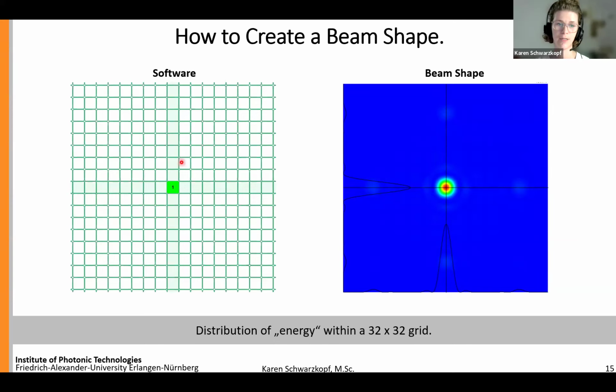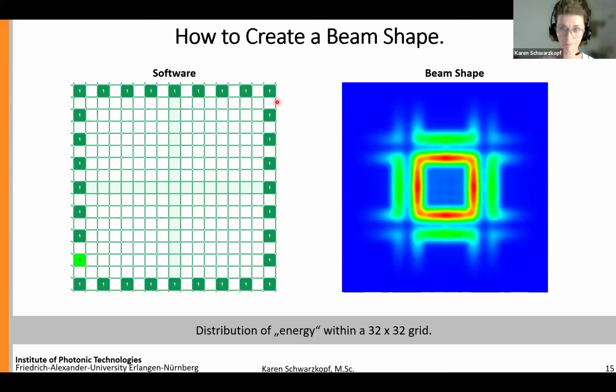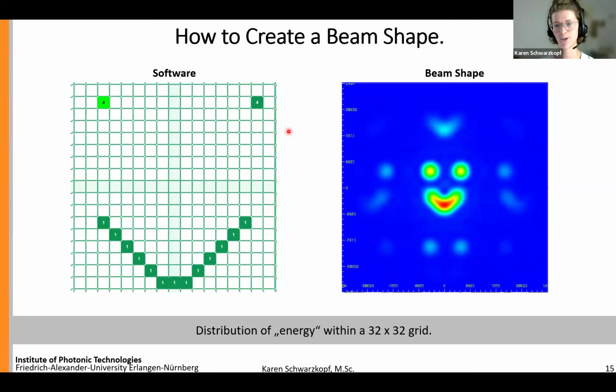What is now happening if you're starting to distribute the energy in different fields is demonstrated here. For instance, for a square-like intensity distribution, you can see by accordingly putting the energy packages in the edges, a square-like intensity distribution is created. And these two beam shapes are rather ordinary, I would call it. And you can see on the next slide that even more challenging beam shapes can be created on the run in a really easy way, just by distributing these energy packages within this grid.